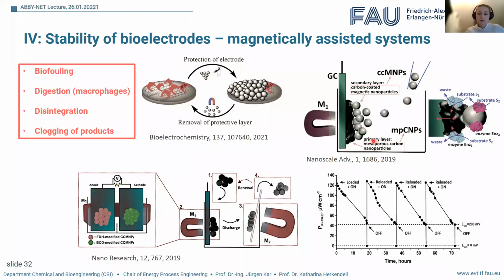Now, certain things that we developed, for example, incorporated magnetic nanoparticles that we could protect the electrodes with. We also developed some systems that could react to different fuel sources available by immobilizing different additional enzymes on magnetic nanoparticles, which then by an external magnetic field we could introduce onto the electrode surface, and therefore also oxidize other substrates available by cascadic reactions.